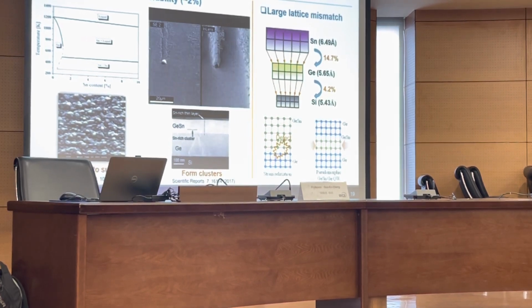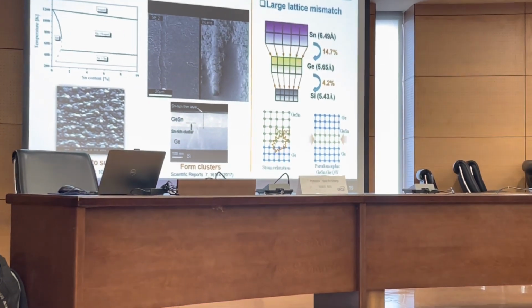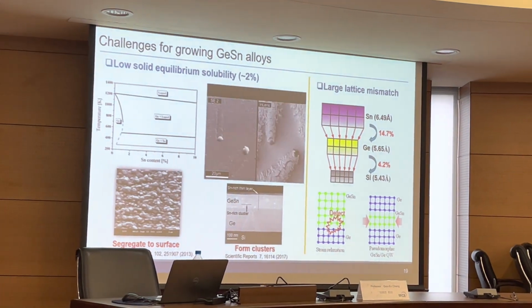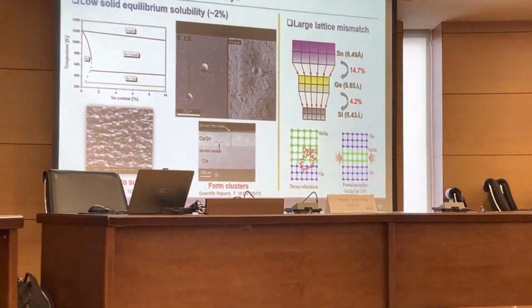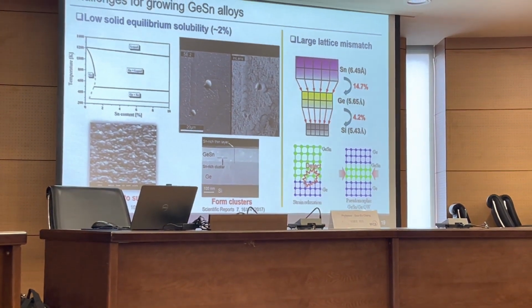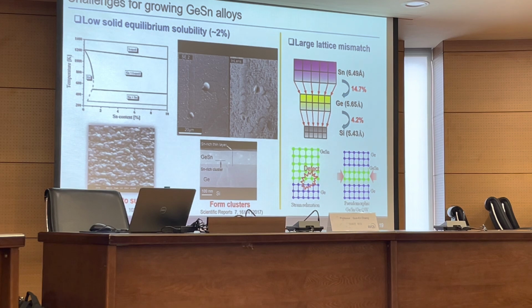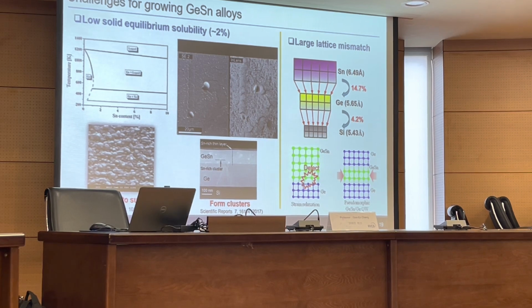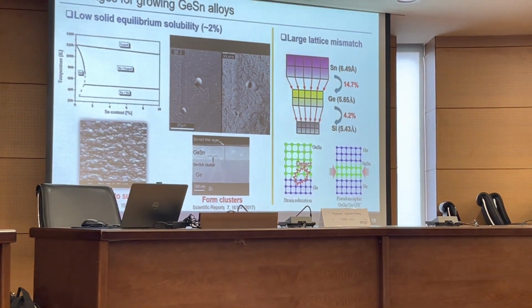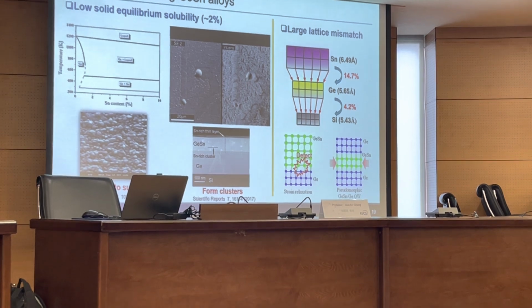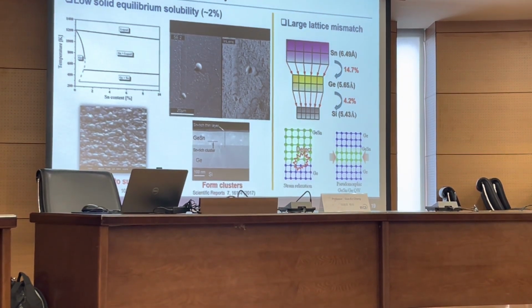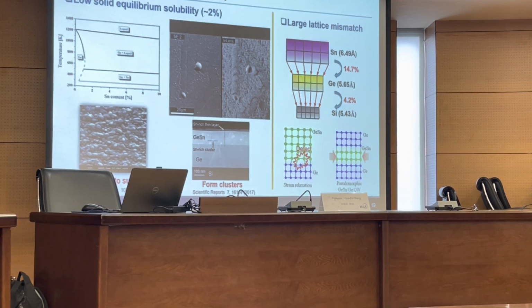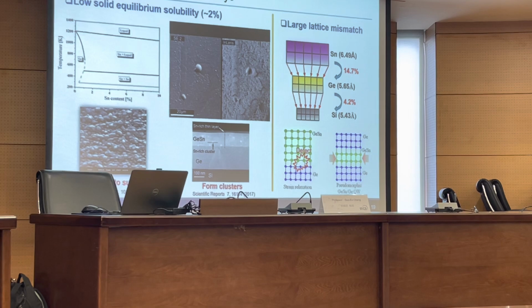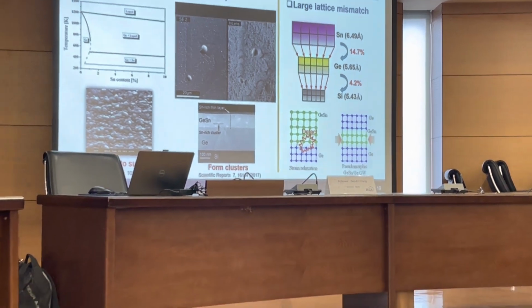This figure shows the phase diagram of germanium and tin. The solid equilibrium solubility of tin in germanium is only about 2%, which means in thermal equilibrium state you cannot have too much tin in germanium. If you have too many tin atoms in germanium, what happens? First, those tin atoms will tend to segregate to the surface. Second, those tin atoms will form clusters in the material. So it's very difficult to grow high quality and high tin content germanium tin layers.